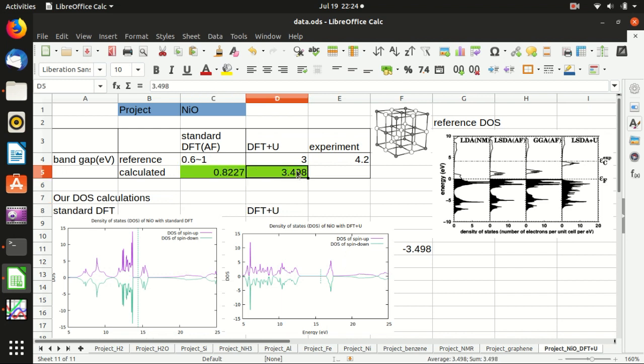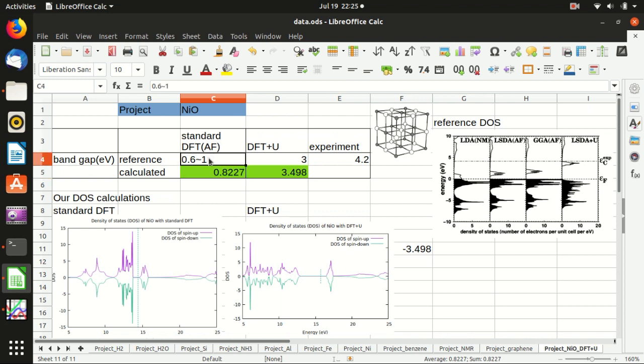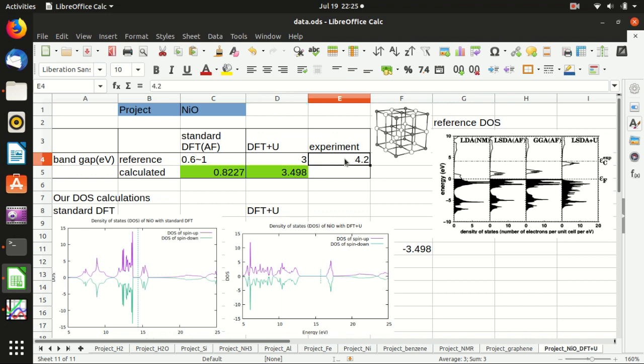So last time with standard DFT the band gap was 0.8 electron volts, and this time with DFT+U it is 3.5 electron volts. This is consistent with what I found in the literature: standard DFT largely underestimates the band gap, while the experimental value is around 4 to 4.2 electron volts. DFT+U actually improves the estimation of the band gap. Thank you for watching and I hope to see you next time.